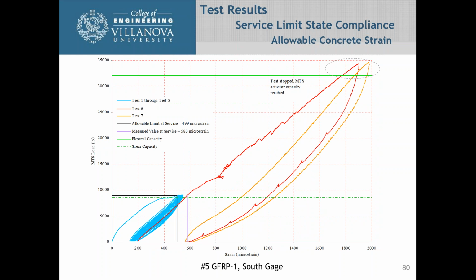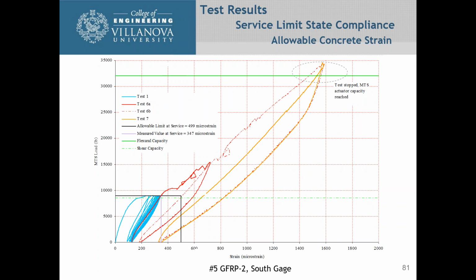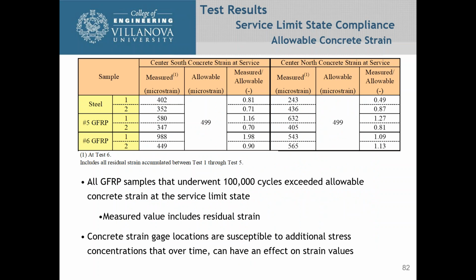And now once we go to the GFRP bars, we had some non-compliance. Looking at the number 5 and looking at the gauge on the south side of the concrete, you can see with the magenta line here that we're actually at 580 microstrains, which means that we're over capacity. For the second one, we're at 347 microstrains.